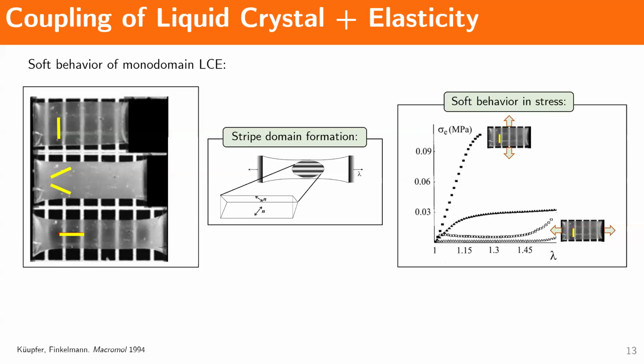So what's happening here is that your mesogen can rotate and reorient to lower your energy, which give you lower stresses. Now, at the same time, you also have to satisfy microscopic constraints, microscopic boundary conditions, right? And so they do so simultaneously by forming microstructures. So what's happening in this particular case is you're loading it under uniaxial tension. You have to also satisfy no-shear boundary condition, right? So they do so by basically forming microstructure, what's called the stripe domain formation, where the mesogens essentially rotate positively and negatively here to be able to lower energy while also satisfying the no-shear boundary condition. Right? So you get this stripe domain formation microstructures that we see.